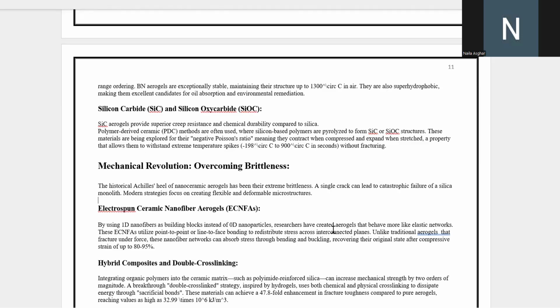Scientists have tackled this in two brilliant ways. Firstly, they stopped building aerogels from tiny dots like nanoparticles and instead started weaving them from long, flexible ceramic nanofibers. Imagine the difference between a fragile tower of stacked marbles and a resilient, springy mattress. These nanofiber aerogels can be compressed up to 95% and then spring back to shape because the fibers bend and buckle without breaking, distributing stress throughout the resilient network.